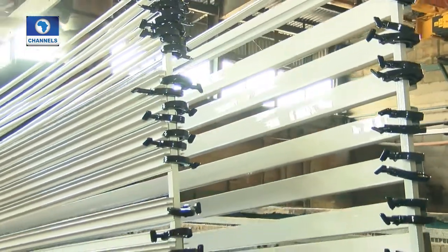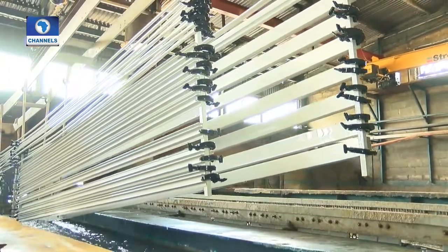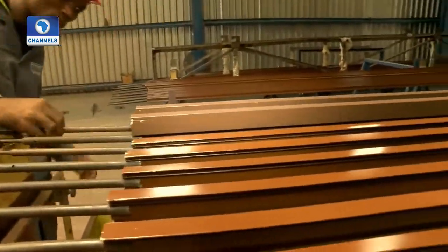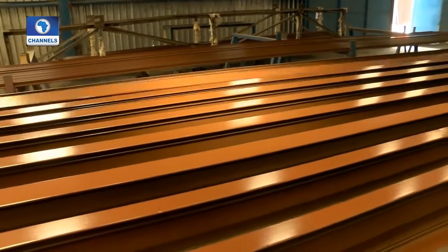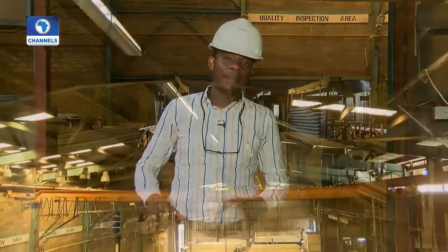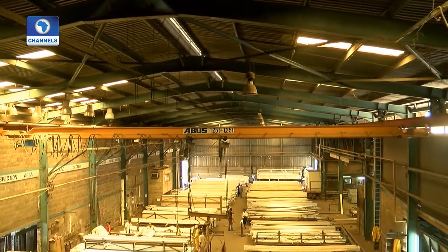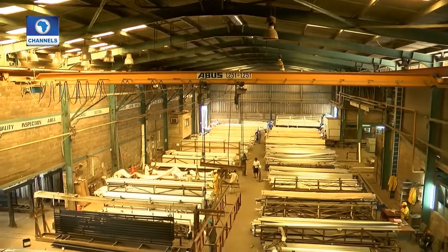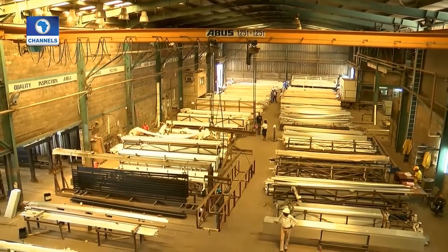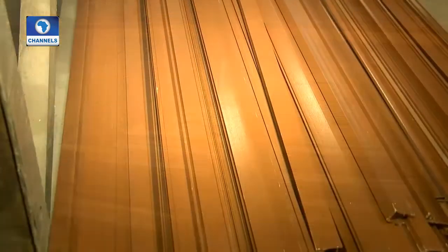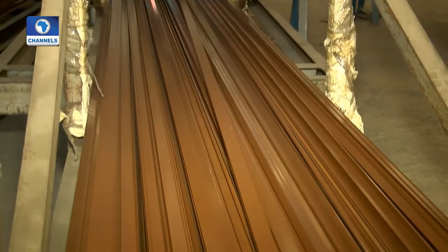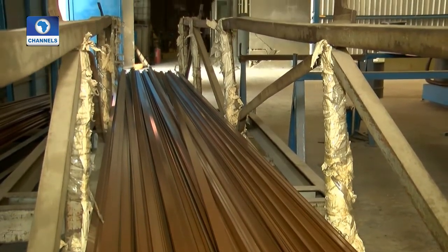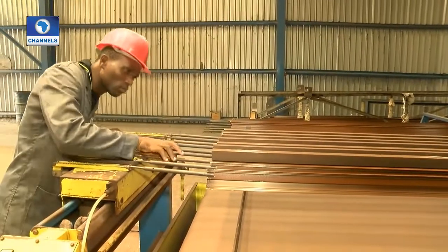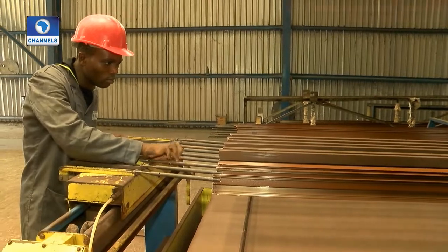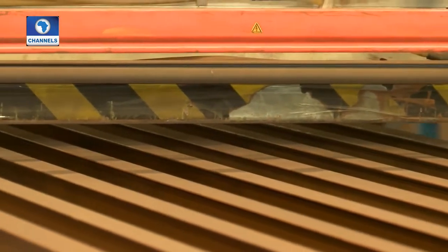This right here is the surface finish section, where the extruded profile is being surface coated. The surfaces of the aluminum profiles produced are taken through a facelift to customers' specification. Here we basically have the powder coating section, which deals majorly with using powder to change the surface of the profile to a specified color, and the anodizing, which is an anodization process that changes the surface of a mill finish profile, or mill finish aluminum, into a customer-specified color. But it's also important to mention that at every point of our production there are what you call QC men. They are always there to check the quality of what is coming out and what is coming in.